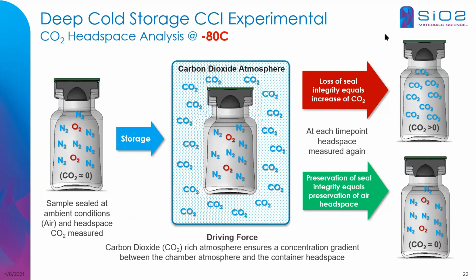One of the other things that we've studied was container closure integrity, and I'm going to show you data both at minus 80 degrees C and then at liquid nitrogen at a lower temperature. In this case, we're using carbon dioxide as the tracer gas, the gas to identify leak. So we fill and we stopper the container. We capture atmospheric gas within the container. So that's why you have a mix of nitrogen and oxygen, atmospheric gas.